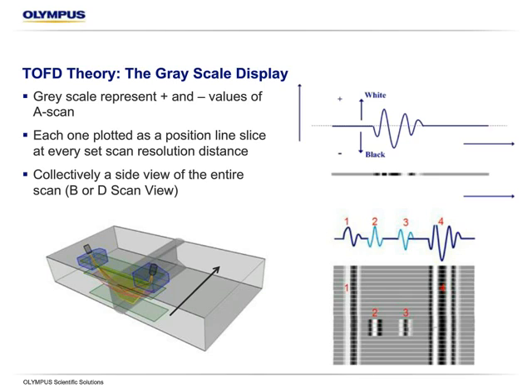So if this was a crack or a lack of fusion laying in a component, not only do we have positive and negative differences between the lateral wave and the back wall, but the uppermost tip and the bottommost tip of that vertical flaw will actually have inverse positive and negative values. This would allow us to precisely position cursors and other measurement tools on top of those tips and get a very accurate assessment of its height.